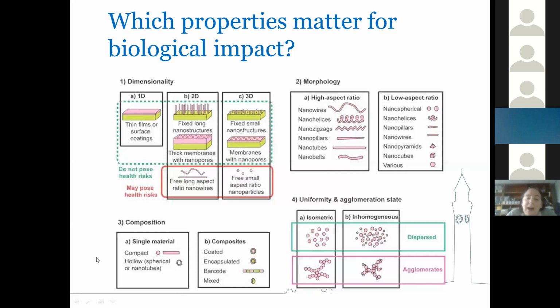The composition obviously will matter because I mentioned already that a whole range of elements from the periodic table can be made into nanoparticles. So for example, one of the major classes of nanomaterials are the quantum dots, and these are again very, very brightly colored materials, very small, usually less than 10 nanometers, and they're widely used in computer screens and in television screens. But they often are made from elements that are themselves quite toxic. So there's, for example, cadmium, selenium, or cadmium tellurium quantum dots. And the reality is that if the chemical itself forming the nanomaterial is toxic, there's a good chance that the nanomaterial will also be toxic.